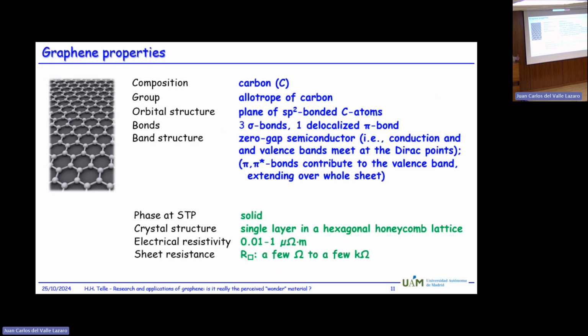And here you have again some of its properties, how it's arranged. Basically, each carbon atom has 3 sigma bonds to its neighbors, and a sort of delocalized dangling pi bond. And this is actually the reason why graphene is also very conductive. So it is nearly as conductive as copper. So in a certain way, this opens up the door to use this material later on, we come to that again, as a sort of a sensor which responds to an applied voltage. And if you change something with your graphene sample, then the current through the sample will actually change.